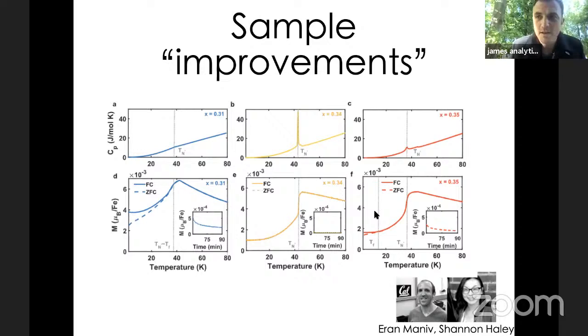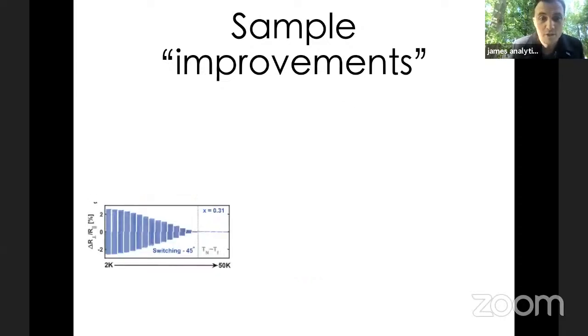But with that, let me take you to something that's a bit more interesting as to how this connects to the switching itself. The sample that we used in our first paper was actually not perfectly stoichiometric. And this is more of an accident. We thought it was 1/3. We measured it to be 0.31, but we thought, okay, well, we still see the switching. Probably we can make the systems more perfect by going to 1/3. But we didn't think that the disorder actually had anything to do with it. So this was the data that basically I just showed you. And what you're seeing here is the temperature dependence of one of those pulse trains. So at the Néel transition, those pulse trains start, and you start to see the switching between up and down. Again, it really shows you that the switching that we see is connected to the antiferromagnetic order.